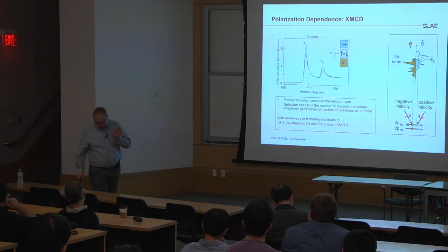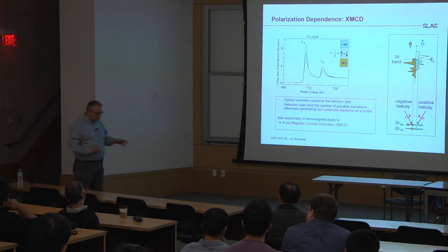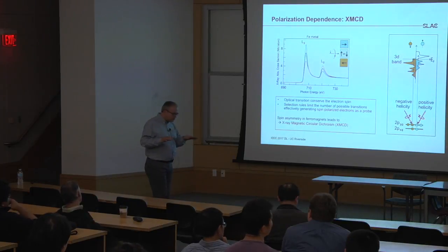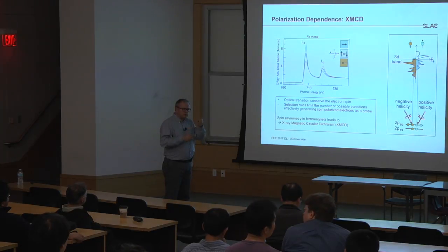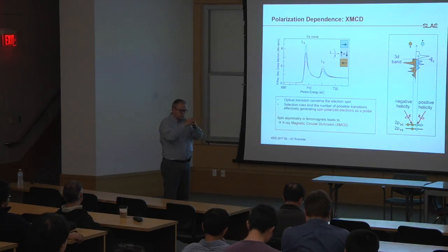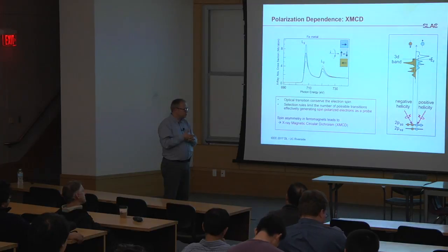A very popular way of trying to model X-ray absorption spectra is using multiplet theory, where you essentially take your atomic orbitals and put them into a particular symmetry, so that you know how much every orbital contributes, in what linear combination, to your absorption spectrum.